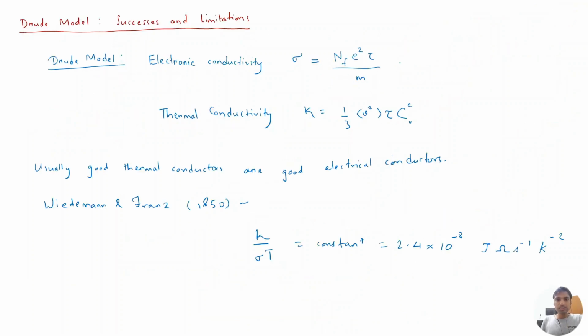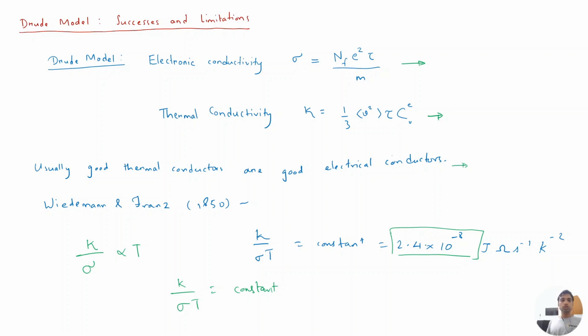So we saw the electrical conductivity in the framework of the Drude-Lorentz model, which is this, and the thermal conductivity, this. And there was this general observation that good thermal conductors are good electrical conductors. This statement was systematically studied by Wiedemann and Franz, and they gave an experimental relation that the ratio of thermal conductivity over electrical conductivity is directly proportional to the temperature. If you assume a proportionality constant, kappa by sigma T will be a constant, and for most materials it is of the order of 10 to the power minus 8, around 2.4. So this is the Wiedemann-Franz law: kappa by sigma T is a constant.